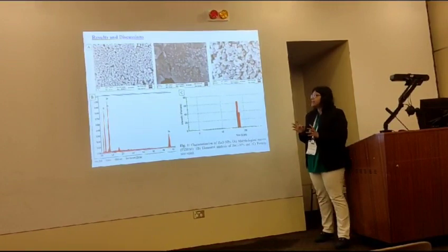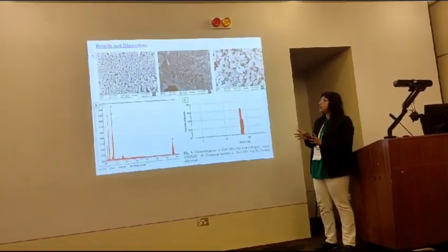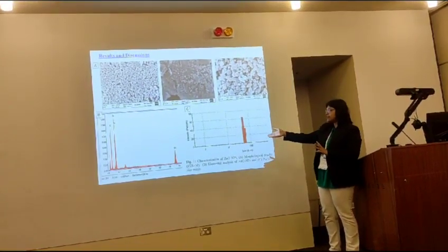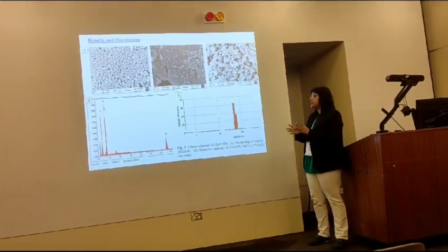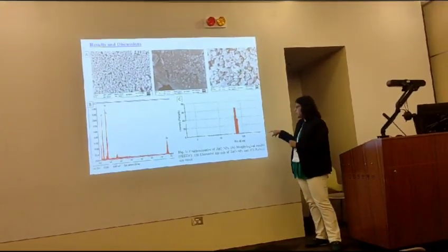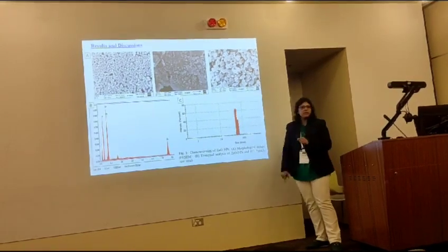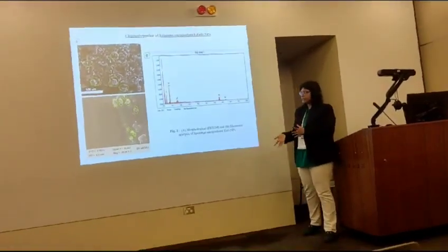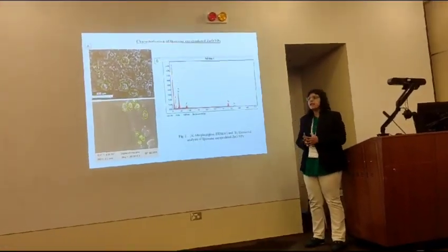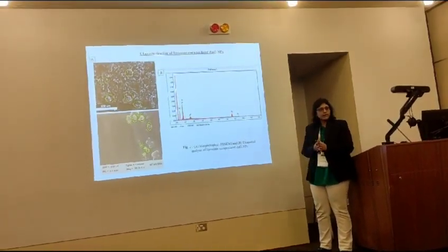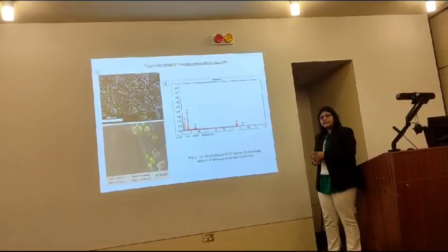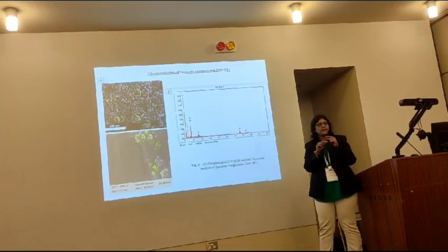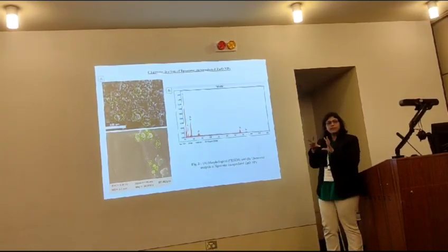These were the results of the zinc oxide nanoparticle which we synthesized, through FESEM. There was the elemental analysis, to check whether the zinc oxide or zinc material is available. And this is the particle size, where we got the zinc nanoparticles within the 100 nanometer scale. After we designed and synthesized the liposome, we tried to coat the nanoparticles with liposome also. We again did the FESEM test, and those rounded yellow structures show that there are liposome structures, round structures with the nanoparticle.